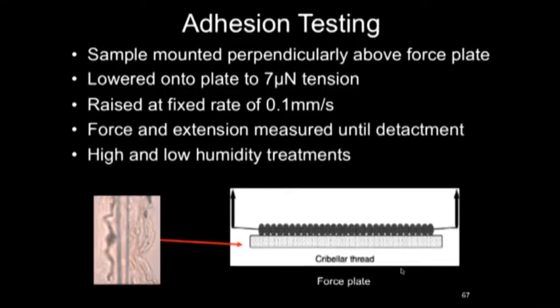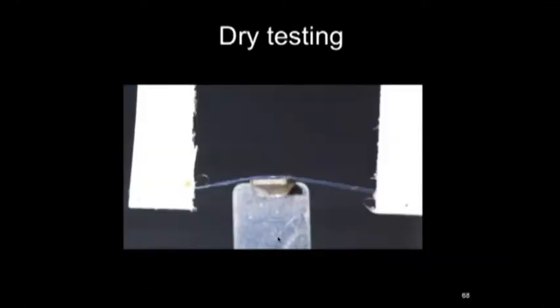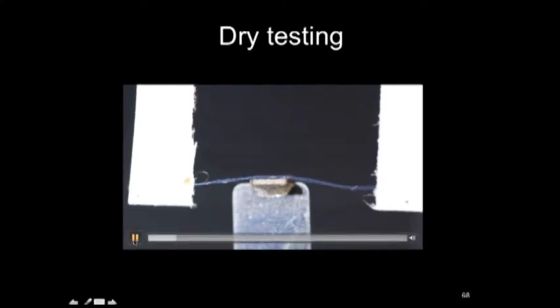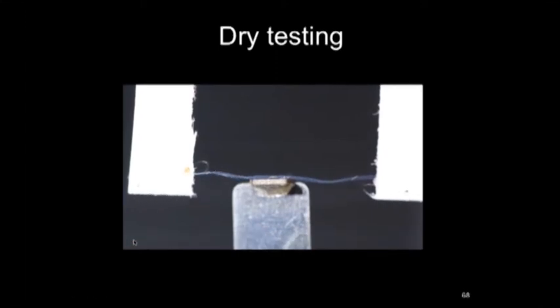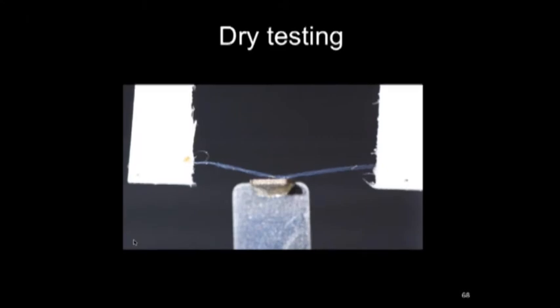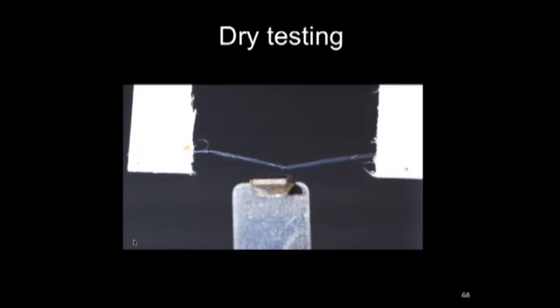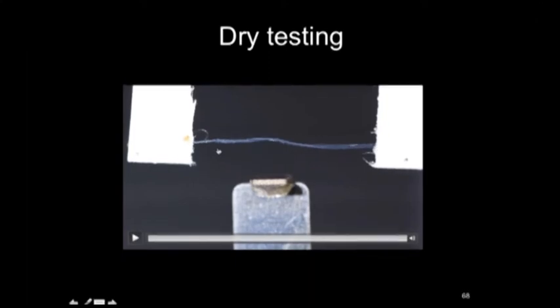So I have a quick video of those occurring. This is in dry conditions. As you can see, we pull up on the fiber and it detaches. Notice that the angle is relatively obtuse and that it doesn't deform very much. But in wet conditions, already at the same tension, it's much more compliant. You'll actually see here that the axial fibers are stretching, and we can see that this angle is more acute, though closer to a 90-degree.